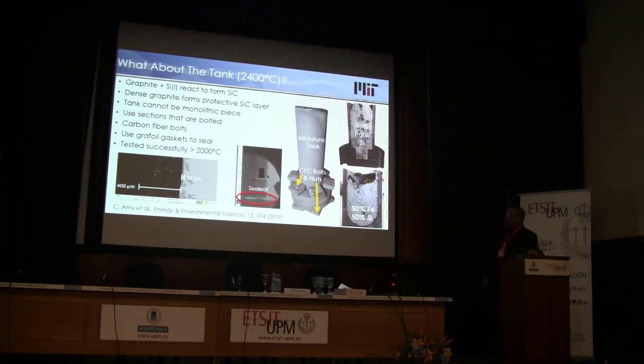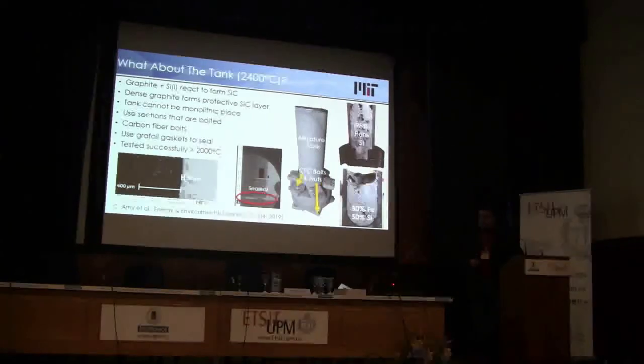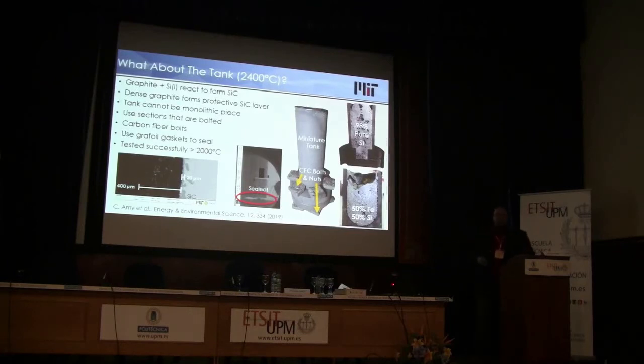All right, so we've also started doing some testing above 2000 degrees C, and I think this is important from one standpoint, which is, I personally was not really a believer in this concept that this system really had any chance of working until we dealt with one particular issue, which is the tank. As I mentioned before, with the pump system, you cannot make the entire pump system, all those pipes, out of one monolithic piece of graphite and cut a bunch of holes in it. The same is true for the tank. If you're talking about an order 10 meter diameter, 10 meter tall tank, you cannot make that out of one giant piece of graphite.